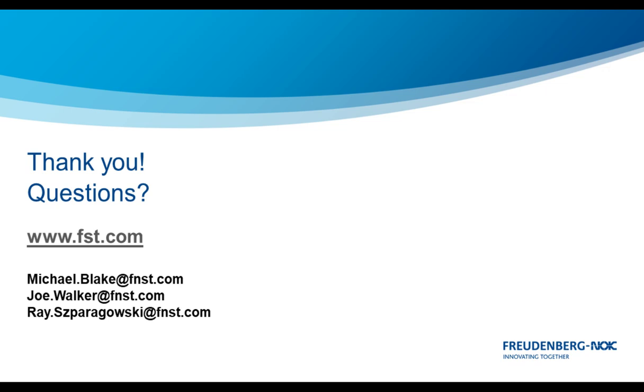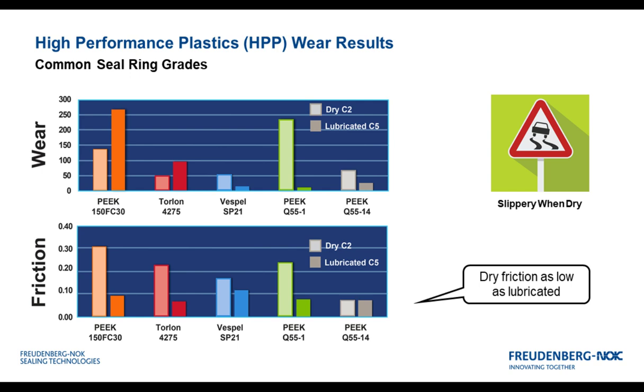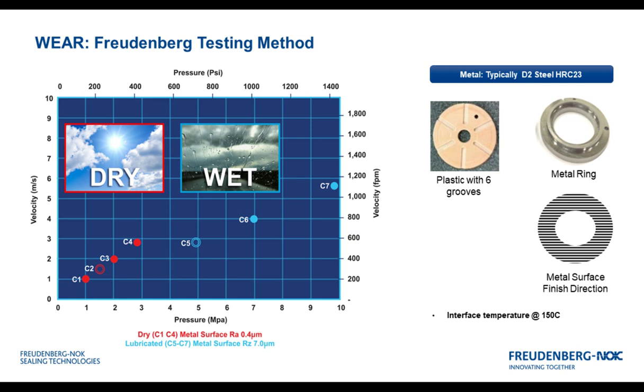Oh, good question. Well, we know that the method we use is aggressive. So when we are testing, we are concerned whether we really see the effects of actual part performance. So we end up not only doing the standard wear testing that we've talked about earlier, but we then actually validate parts, and we've seen that we can correlate the wear performance that we see to the actual part performance. But it's important to note it really is about understanding failure modes.